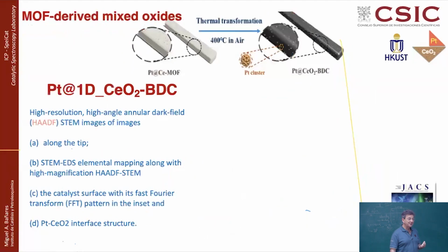We wanted to maximize the activation of oxygen, to maximize the interaction of cerium with other elements, to see if we can create more defective ceria, reduced ceria at interfaces with metals, not only gold, but other metals, like for instance platinum, and see if we can get that. So we were working also on materials that are making cerium oxide in the shape of a rod. And some of you were working with metal organic frameworks. So basically we're using a metal organic framework, but as a precursor for an oxide.